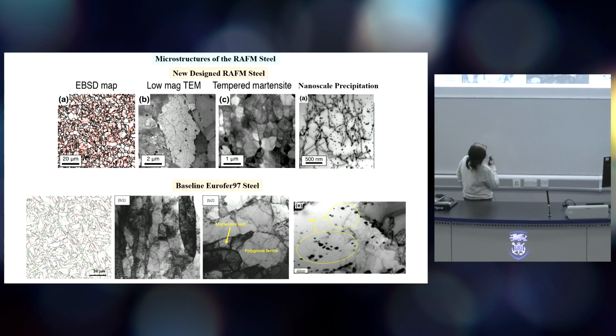The images shown above are from the newly designed steels, and the bottom images from the EBSD and TEM are prepared from the current Eurofer 97 steels. We can find that we achieved bimodal structures, with larger ferrite grain size, and we also achieved nanoscale grains in the martensite phase. This is a typical martensite. The bimodal structures improved the ductility without consuming the strength. Importantly, we have extremely high dislocation density in the ferrite phase, and those dislocations become the precipitation positions, which maximizes the precipitate number density.